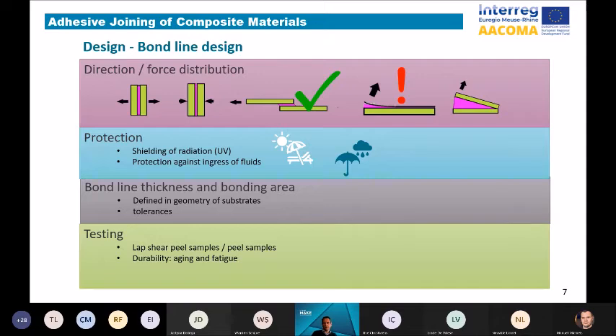When the materials and the geometry are defined, testing the adhesive bond is highly recommended. Testing can be done on coupon samples or on real models. The testing is normally done in combination with accelerated aging cycles to test the durability. And which cycles you choose depends on the outcome of a risk analysis. Testing can typically take 1 week or maybe up to 5,000 hours.